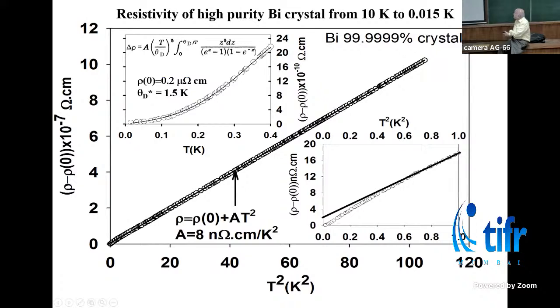The other thing is the resistivity. Bismuth is supposed to have a T-square dependence of resistivity right down to lower temperatures. But it deviates at around 400, 500 millikelvin. It's no longer T-square. Worse, when you go down to lower temperatures, it behaves like T to the power of 5. So there is something changing at 500 millikelvin in bismuth. The electronic structure or something is changing, which we are unable to see. Ideally you can do a Fermi surface, but doing a Fermi surface at this temperature is going to be a very, very, very tough task.